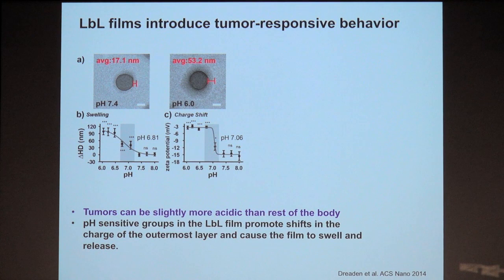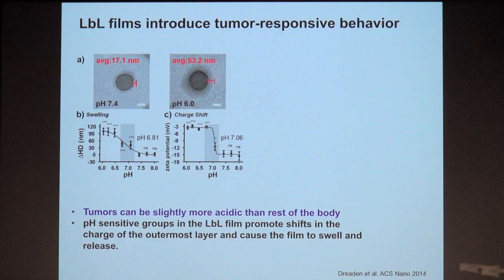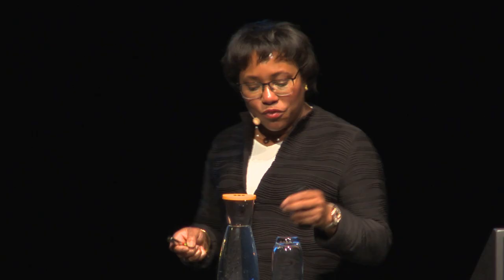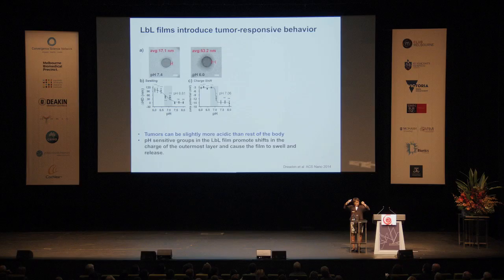And the reason for this is because it turns out that there are acid groups, carboxylic acid groups, that exist as COO-. For those of you who didn't like chemistry a lot, this is only a small amount of chemistry. COO-, you add a proton, and it goes to COOH, and it loses its negative charge. So what is happening here is that we're doing that to a lot of these negatively charged groups. And if we do that, we're erasing negative charge. Because the complex was built on plus, minus, if we erase negative charge, then we lose those ionic crosslinks that were holding things together, and the film swells slowly. At very low pHs, it can release our siRNA that's inside.